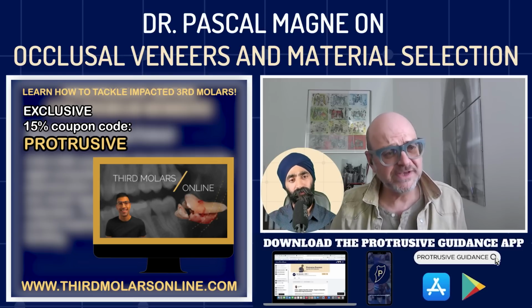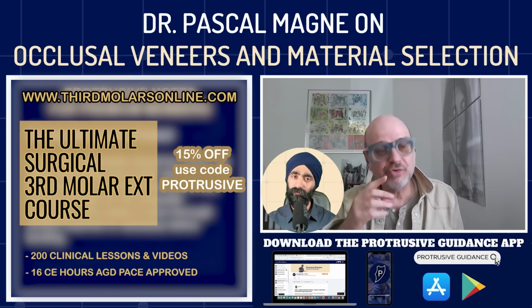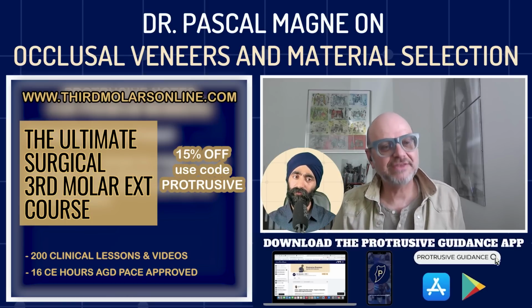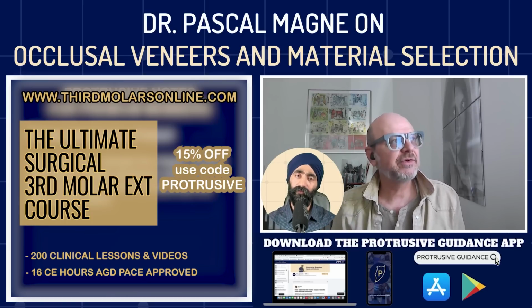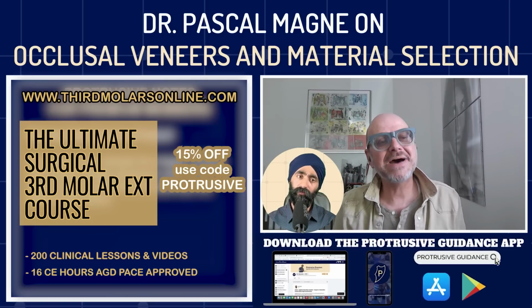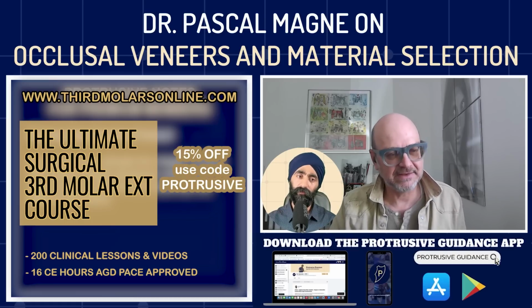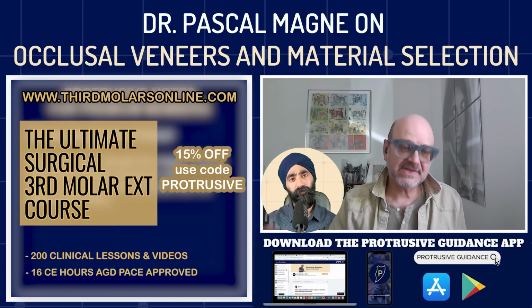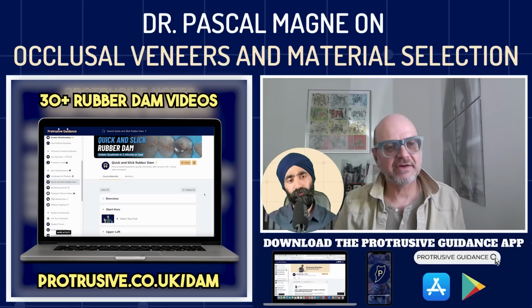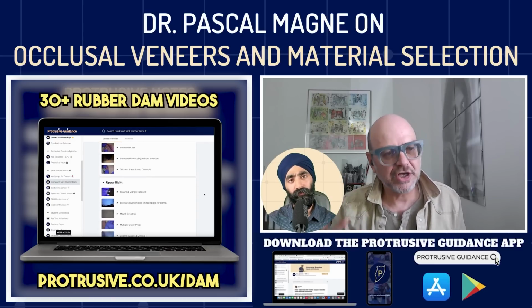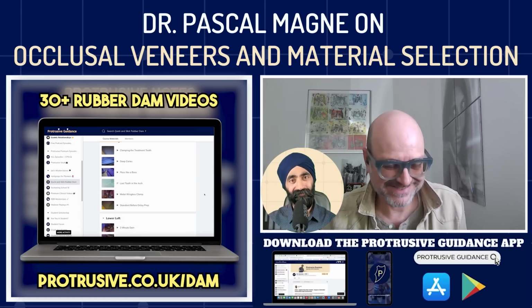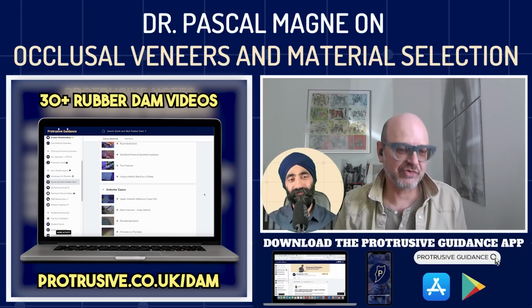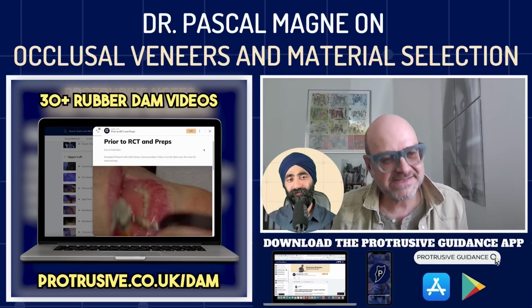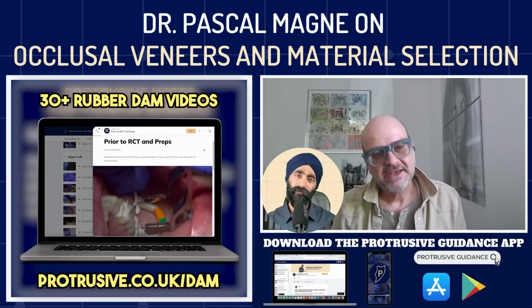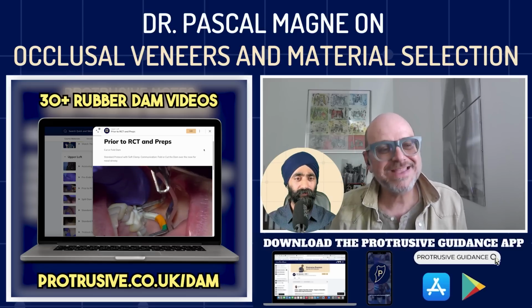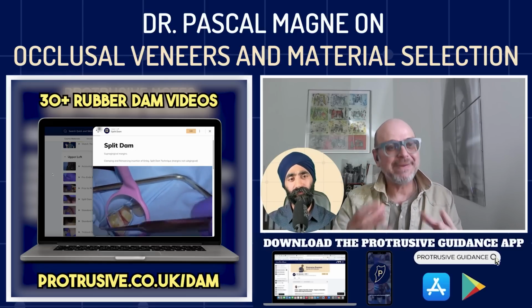So what I like to do is to air abrade them. I would preferably use CoJet. You can use aluminum oxide, but I will preferably use CoJet to maximize the effect of the silane. And then you use the silane. And the silane, you have to be careful because this is where there's a lot of misuse of the silane. The silane has to be placed for no longer than 30 seconds wet and then air dried. You never let the silane dry by itself.